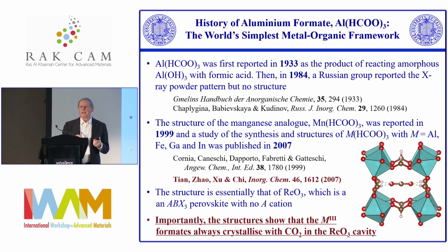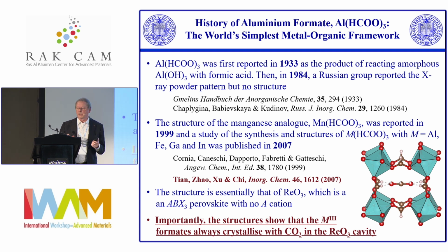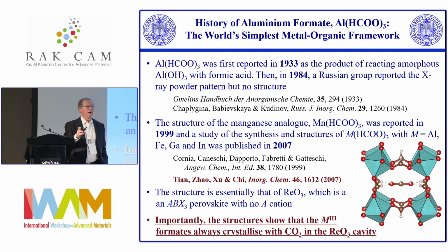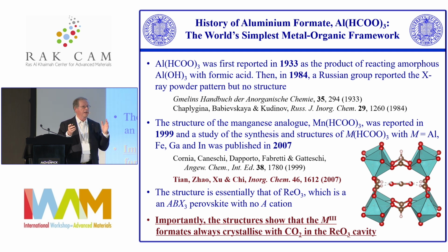When I looked at this paper, there's something striking about it, because this structure will only crystallize if it's got carbon dioxide in the cavity. In the title of that paper was something like templating of the formation of aluminum formates by carbon dioxide. The carbon dioxide sits in the ReO3 cavity, and I'll show you in a bit more detail in a minute, but it's locked into place by hydrogen bonding with the formate hydrogens. And so I had two thoughts about this. One, can we get the carbon dioxide out without destroying the material? And if you do that and have a pristine activated version, will carbon dioxide go back in? Because there's clearly something special about carbon dioxide and this structure type.